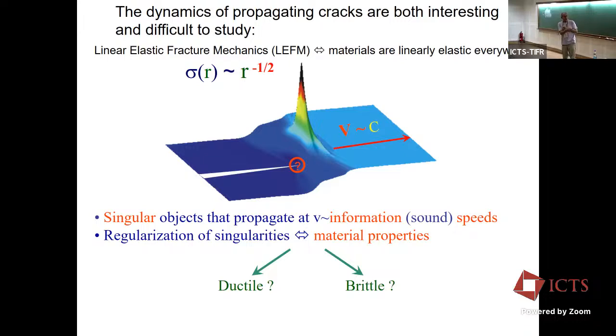nature, or how the material, flows around this singularity in order to regularize it. And that's something that's not very well known, how it's done for different materials. For example, crystalline materials create defects. So you start to get more and more defects and dislocations. But glass, for example, is an amorphous material, so there aren't really any defects in glass, although the people in glasses might differ on that.